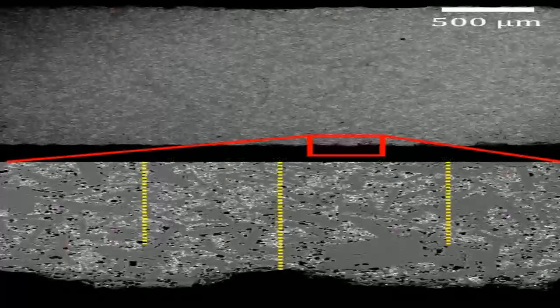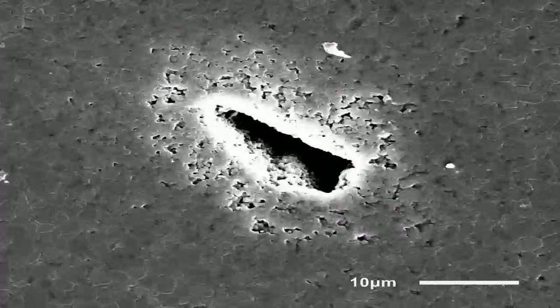Interesting, and did they figure out what controls how good that alignment is? Yes, they showed that factors like the length of the printing nozzle and how much solid powder was loaded into the paste affected the degree or strength of this alignment. Longer nozzle, higher loading, generally meant better alignment in the shell. Okay, so you get aligned platelets, especially near the surface of the printed line.